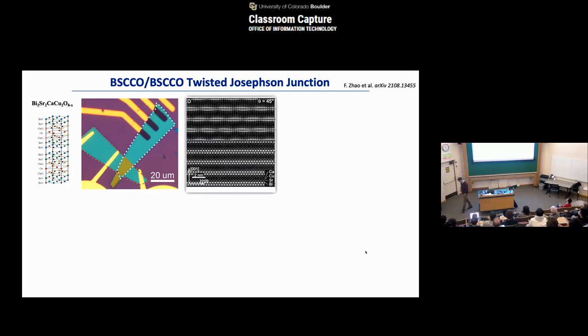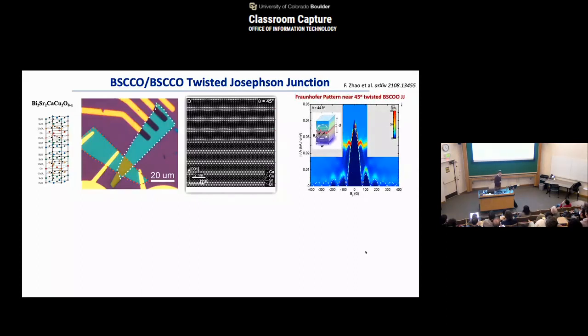If you just do it right, as you see in the cross-sectional TEM images, in this particular sample we put the twisting angle at 45 degrees. And I'm going to explain why 45 degrees is really special. As you see in the TEM images, if you do it right, the interface is extremely clean, right? This type of crystal or structure can never be made by MBE because of the compatibility of the interface, but we can nicely put them together with this technique. And one can see that in this type of interface, if you measure the Josephson current flow, there are some amazing things.